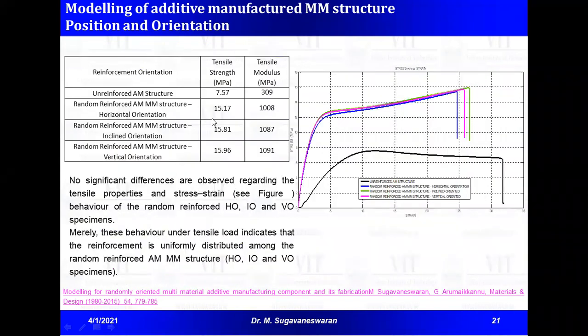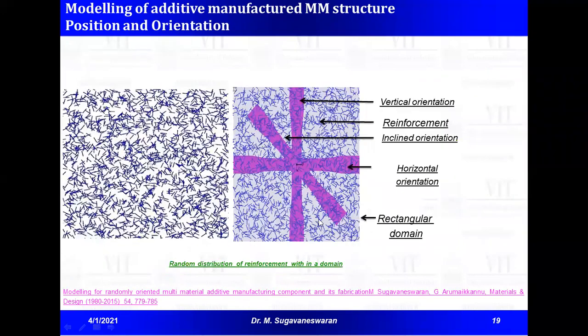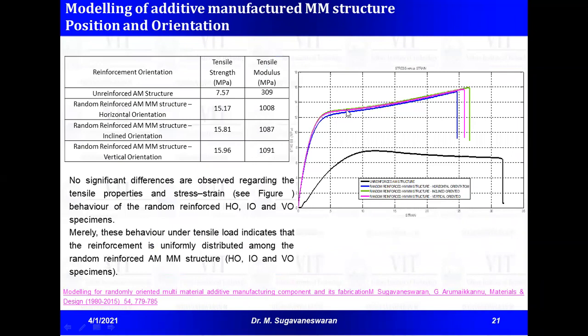And these samples have been printed and tested, because the samples we have taken out here are for tensile testing. So the model to sample is printed, and the stress-strain response of the printed samples is shown in this diagram. If we look, there is a minor variation in ultimate strength, but the behavior of the material is almost constant. Though we have generated the reinforcement randomly, the uniformity is maintained, only at the end it depends on the crack propagation region and how the reinforcement is positioned with respect to the crack propagation region.